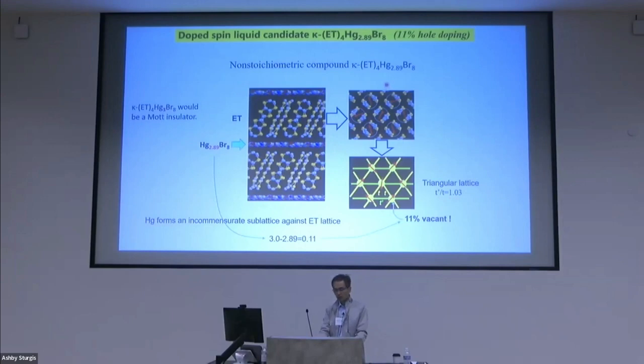The clear difference from the previous spin liquid material is the non-stoichiometry of the insulating layers. The mercury and bromide constitute one monolayer. This is the insulating layer. And the interesting point is the content of mercury is 2.89. So we cannot control the content of mercury because mercury is a very curious element, and some mercury forms incommensurate